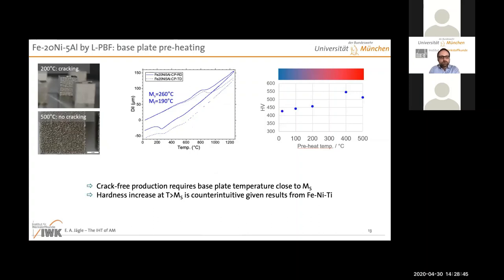Okay, so let's switch tracks again and go to a topic that we really have not understood completely yet. This is again the alloy that I showed you earlier, the iron 20 nickel 5 aluminium. But this time it is not processed by DED, it is processed by LPBF. LPBF has a much smaller melt pool, much higher cooling rates, and much less effective reheating. And what happens? Well, you keep the entire aluminium in the solid solution, and that is just a very brittle material. So you get these cold cracks afterwards.